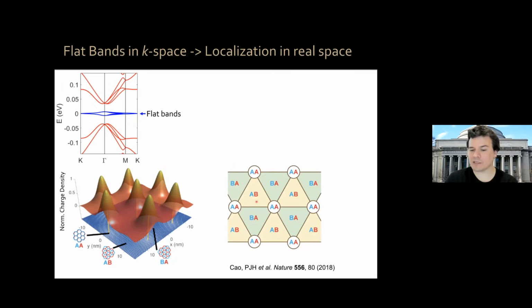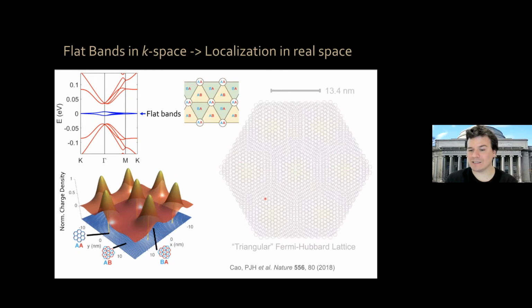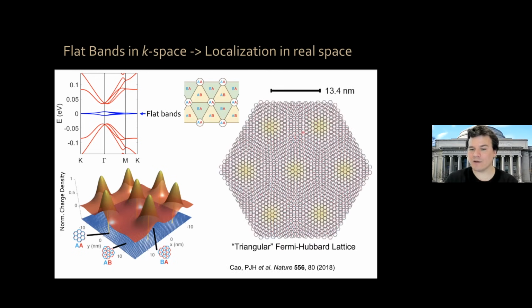And these regions are separated by regions of AB and BA stacking where the electrons do not like to be. Okay? In a slightly more realistic schematic, this is what you have. You have these yellow regions of AA stacking where the electrons like to be. This is what's going to form our triangular Fermi-Hubbard lattice by analogy with the cold atom systems, okay? And the separation between these AA regions is of order 13 nanometers.